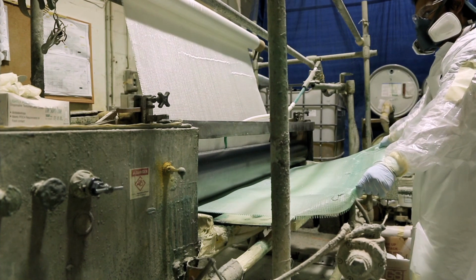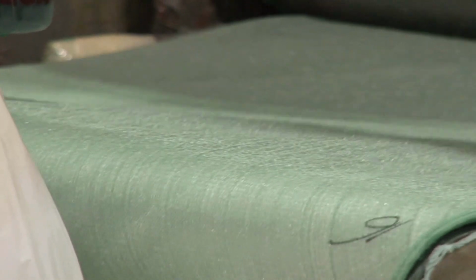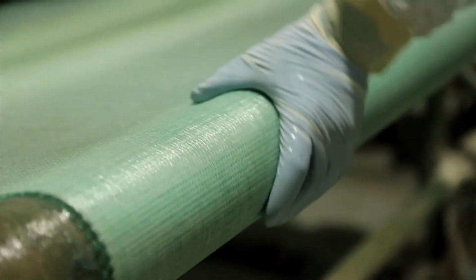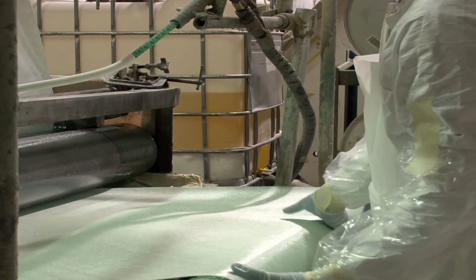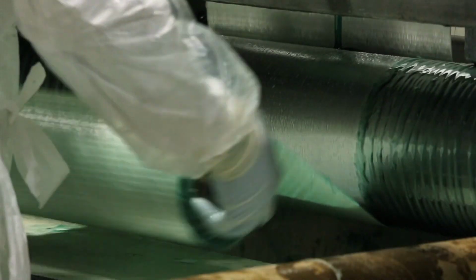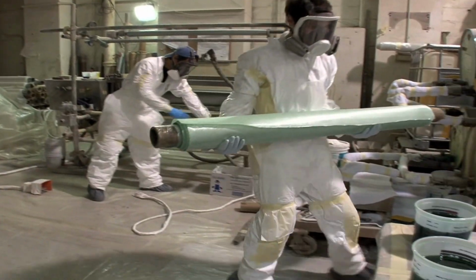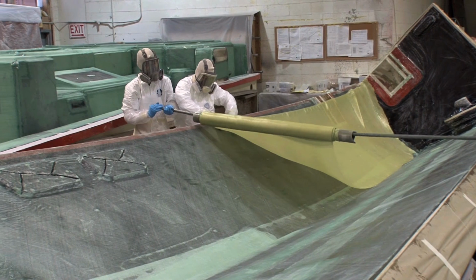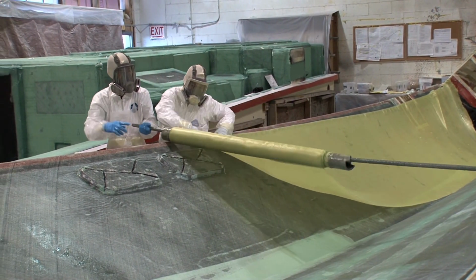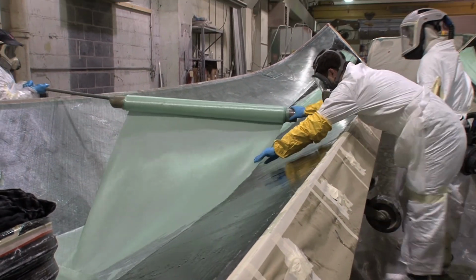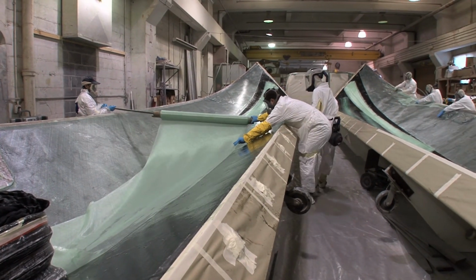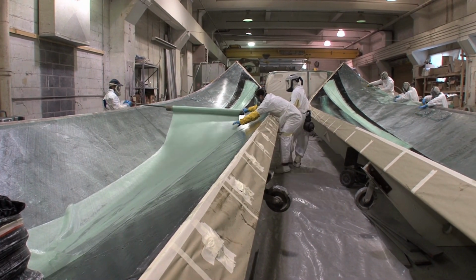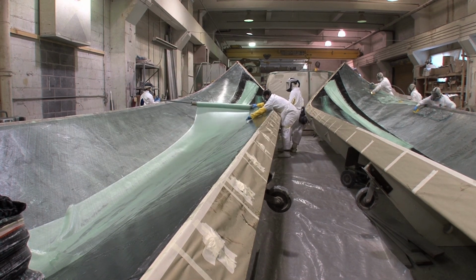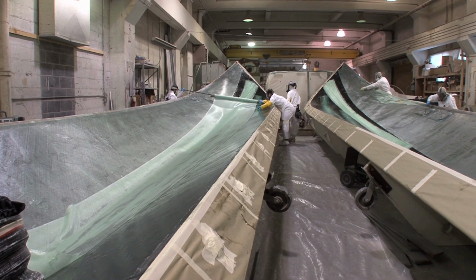Here you can see high-strength, continuous strand, biaxial and triaxial glass fiber being run through high-pressure rollers, completely saturating every fiber, squeezing out the excess, and limiting the resin content to an exact 60 to 40 glass to resin ratio. The hull's built in 2 halves so that we have easy access to every inch of the hull to control and inspect the laminate. Note how the fibers are laid to run continuously over the entire length of the boat. It's not hard to see why an MJM is much stronger and will last much longer than boats built with glass that is chopped into short strands and floated in a lower strength resin.